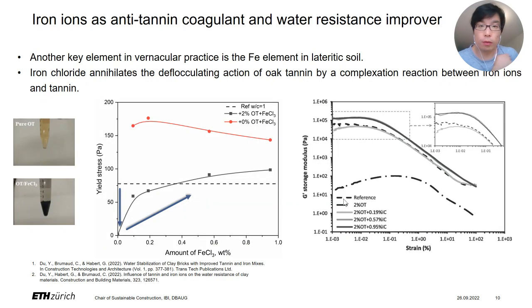So after knowing tannin can be used as a dispersant, we need to think about how we can remove this dispersant effect while maintaining or even increasing the water resistance. If we look back at the vernacular practice, another important element is the iron-rich soil. But we don't have this soil around the world. So we simplify this practice into an additive solution. We chose iron chloride one.